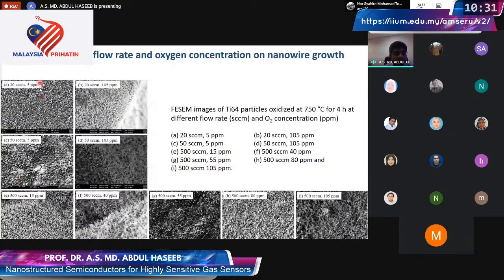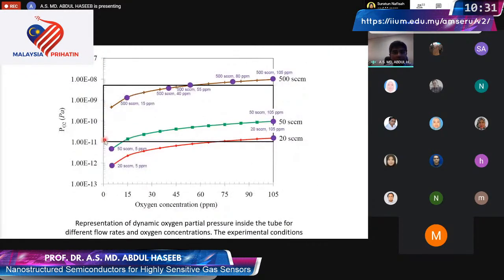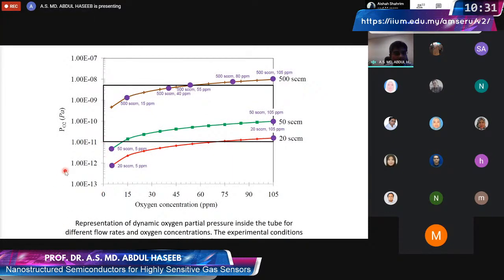In fact, when we document all this in a systematic way, we prepare a map of where we get the nanowire, and we plot in one axis the dynamic partial pressure of oxygen and the oxygen concentration in the tube. And we see a box within this. In our experimental condition, we find that the nanowires grow only within this box. We have carried out tests, and the test conditions are all the purple dots. And we find that the purple dots, which are within this box, give us good enough nanowires for our sensing application.